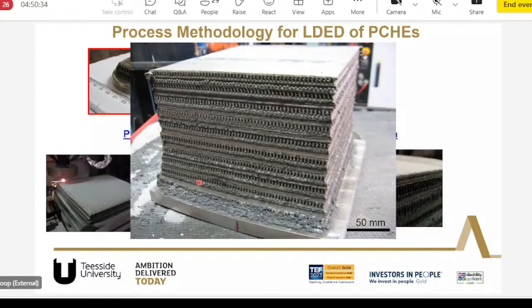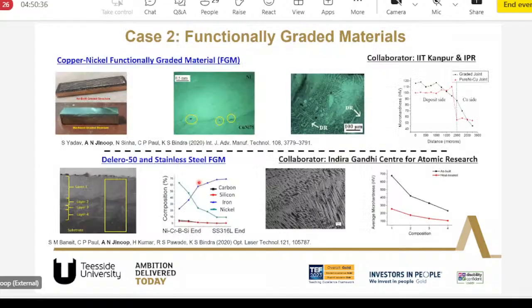Then I worked a lot on functionally graded materials. This was published around 5 years back, where we tried to develop this for IIT Kanpur and IPR and for IGCAR as well, where we did copper and nickel FGMs, and we did Delero and stainless steel FGMs. Functionally graded materials, for those who are new to this, are materials that are manufactured with a gradual change in the composition from one end to the other end. So as we move from one end to the other, we have a slow change in the material composition.